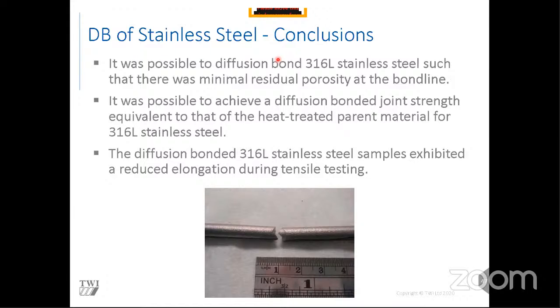Can we diffusion bond between different metals? Yes, we can. If we're lucky, we can diffusion bond different materials using no interlayers, so a solid bond. But the number of alloys where they're compatible is few and far between. There are a few though, but quite often you need to use an interlayer to create a transient liquid phase diffusion bond, or make use of a eutectic phase if it exists for those different materials. So it all depends on your combination of what approach we would take.